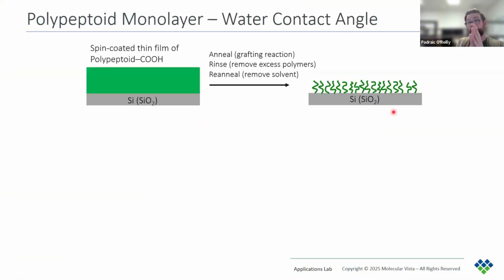Now finally, we looked at some more monolayers and some potential shortcomings of water contact angle measurements and ellipsometry when you rely on these alone. So polypeptoids, which are polypeptide-like molecules designed for binding to silicon, were used for this study. Initially starting off with the carboxylic acid binding group.